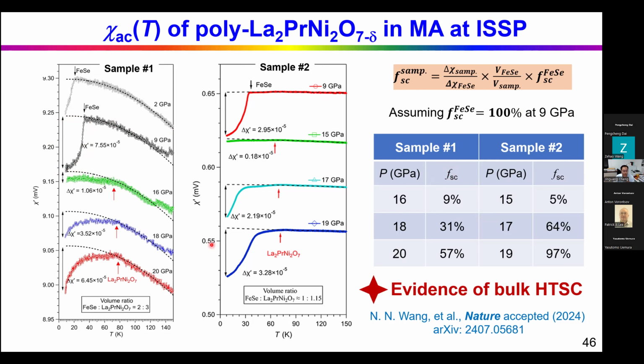For this sample, at 20 GPa, it can reach about 57%. But this is at about 80 Kelvin. You see this is still decreasing quite rapidly, so at the lowest temperature, the volume fraction would be higher. For the second sample, it's much better. The volume fraction can reach nearly 100%.